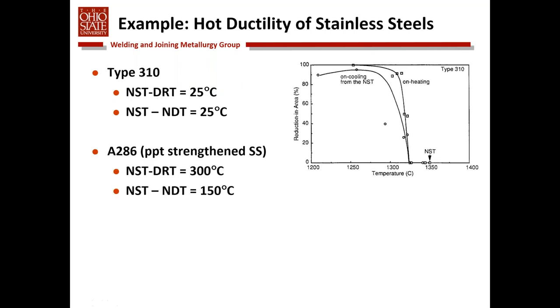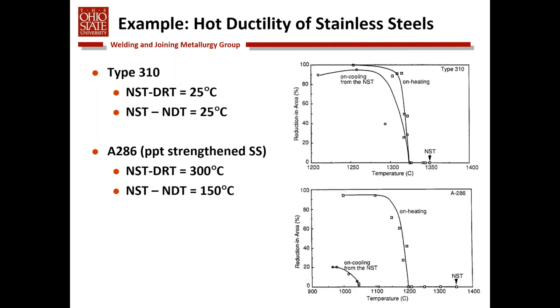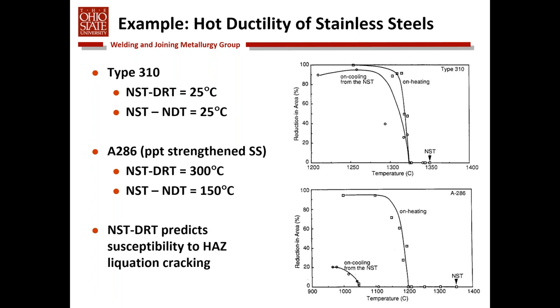If we contrast that to A286, which is a precipitation strengthened stainless steel containing titanium, we see a much different behavior where now the nil strength temperature is about the same as the 310, but the ductility recovery temperature on cooling from this temperature is down around 1050 degrees C. And so now this value is much, much higher, by an order of magnitude, than for type 310. And we know for certain that A286 is very susceptible to heat affected zone liquation cracking. And so the test is predictive of the actual behavior.